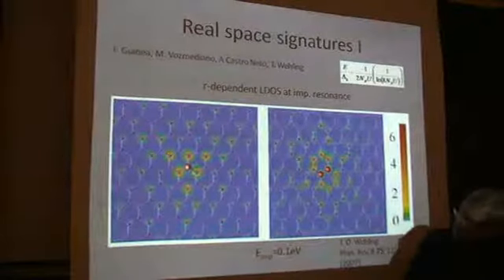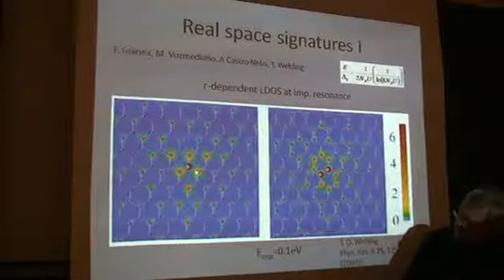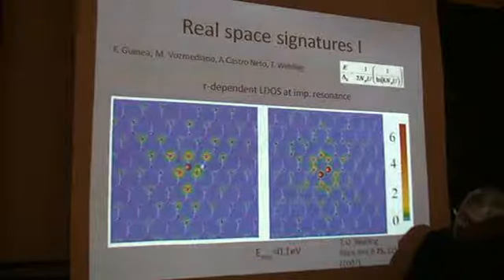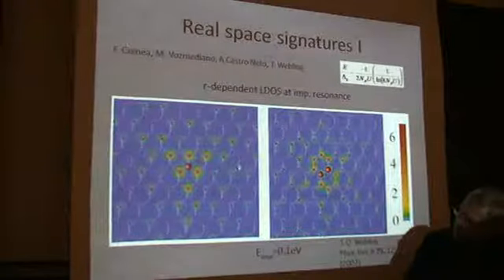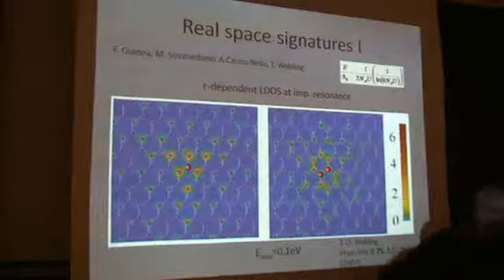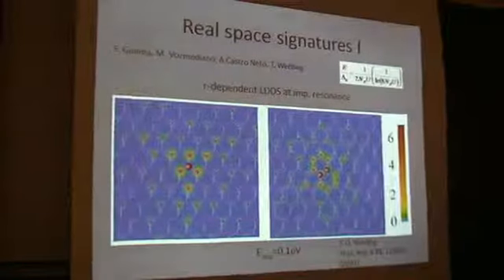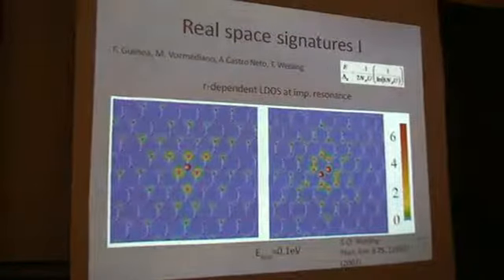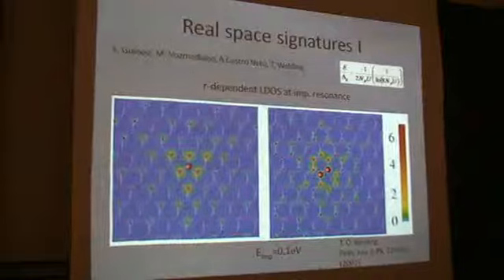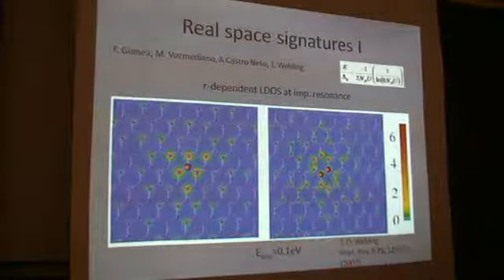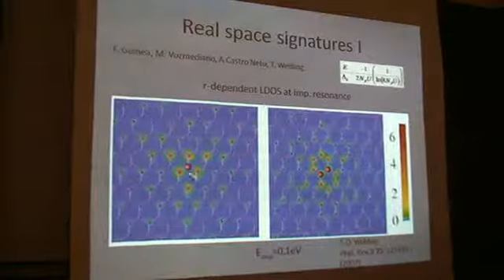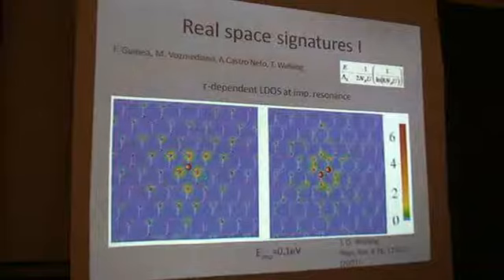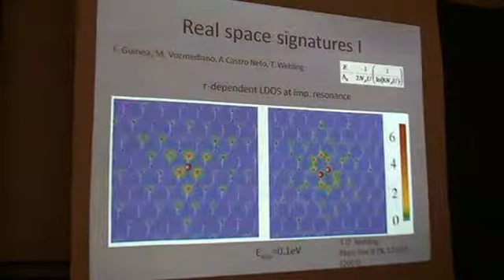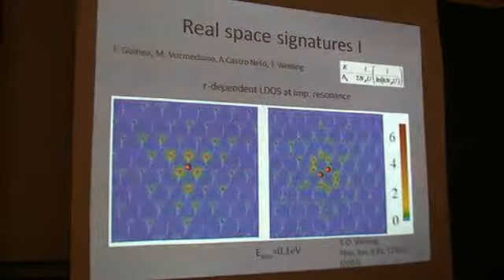So you see, if the impurity sits on the A sublattice, B is bright, A is dark, B is bright, A is dark, B is bright, A is dark, B is bright. So you have a ripple. If you sum all these ripples over the total filled states, you get what you know from the textbooks as a Friedel oscillation. But the advantage of STM is that you can do it one state at a time, at a certain energy. And that's how this localized state looks. It has an envelope, it has beating, which is, in this case, 2kF.